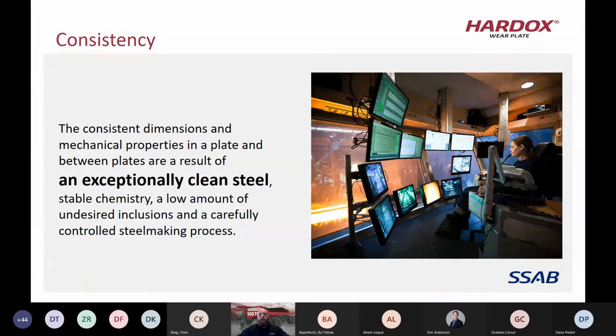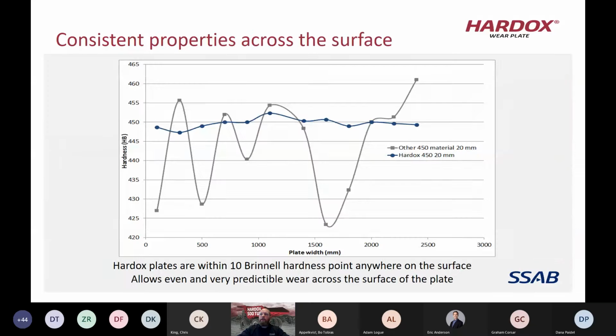So really, one of the big benefits with Hardox is consistency. We work a lot to make a very clean steel and make sure it is very consistent. What I mean by consistency is that we want to see consistent properties across the plate surface and through the steel. This is a chart showing a typical AR 450, the gray line, that's 20 millimeters thick, and then the blue line is a Hardox 450, also 20 millimeters thick. With Hardox, you can see how the line is very close to that 450 Brinell, where the competitive AR goes anywhere from 420, 425 Brinell all the way up to around 460 Brinell.